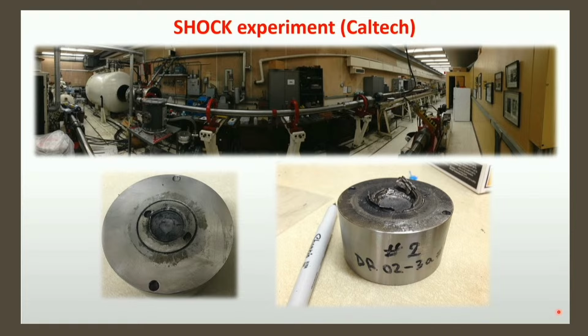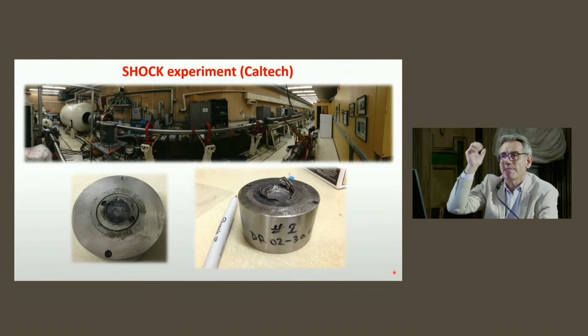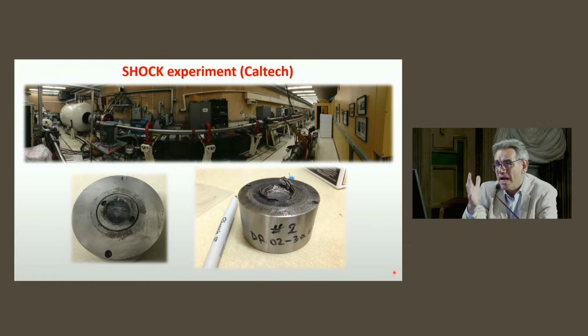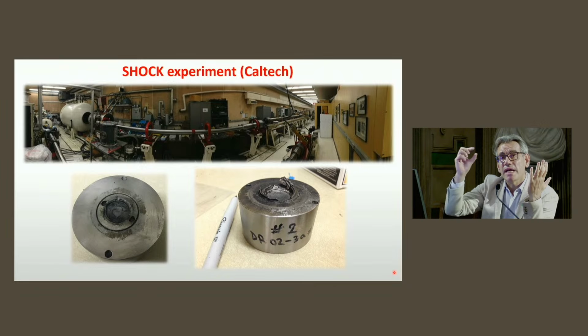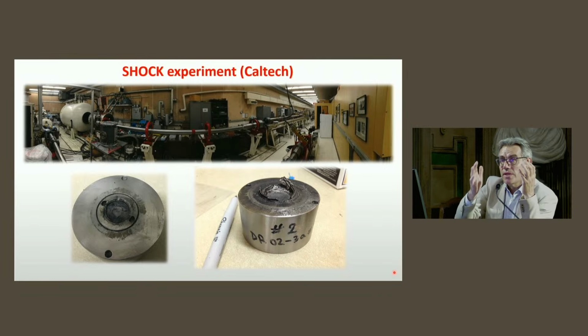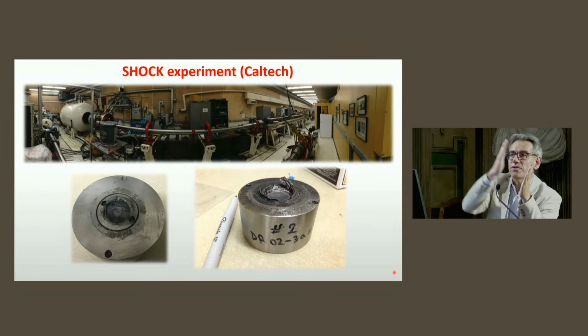They have a very long gun which accelerates a projectile, a metallic projectile, at a very high velocity, about 1 kilometer per second. The only thing you can choose is the target. The metallic projectile is tantalum, and it is accelerated over a target, which can be a single disk, or a combination of different disks stuck together.